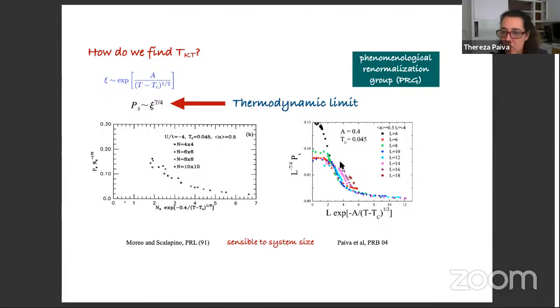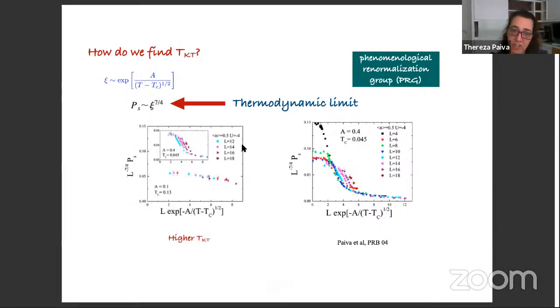And when we did this, I was going to say nowadays, but this is 16 years ago, that we reached larger system sizes. We see that the collapse is good here for the smaller lattice sizes, but that the bigger lattices are far away from collapsing. So what we did is change the parameters here, and we found that the ordering temperature was really a lot larger than was earlier expected because of the larger system sizes that were available then. So we get a higher TC than was expected before.